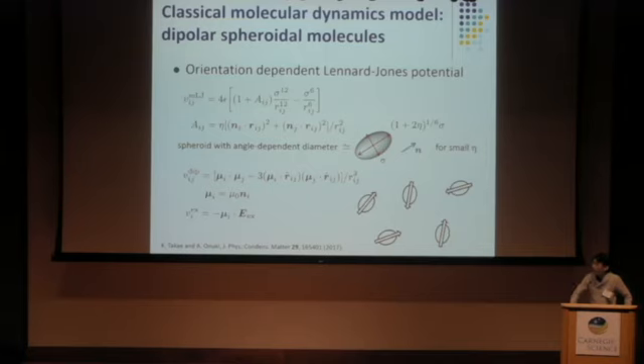This is just one example using the antiferroelectric phase. The mass of the particle is the scale unit, so it is set to unity in the numerical simulation. The moment of inertia is calculated by assuming this particle is a corresponding spheroid. Suppose you double the dipole moment and you double the moment of inertia, do you get the same results or not? Very different. The magnitude of the dipole moment is chosen so that the three phases, paraelectric, ferroelectric and antiferroelectric, are realized in the numerical simulation.